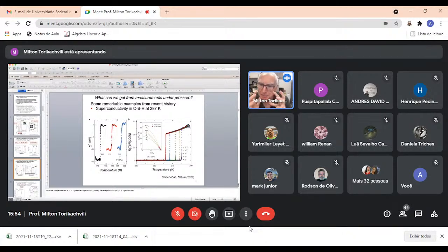How do you know this is the whole sample being a bulk superconductor? Well, this is sort of confirmed over here where you measure the AC susceptibility, which is more of a measurement of the volume than what the resistance is. The resistance, if you have just a percolation path that is superconducting, you would get zero resistance. But here you see that there's a very large change from the normal state to the superconducting state, confirming that this is the volume that is becoming superconductor.